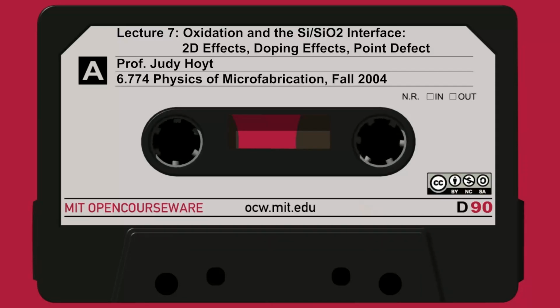We also talked a couple of times ago about interface charges that come along with oxidation. And this model on slide 38, while we're talking about atomic-level things, is an atomic-level cartoon or picture of what is actually causing the fixed charge and the density of interface states. Here's my amorphous SiO2 up here, and my crystal silicon. In the near interfacial region, there are believed to be a few interstitial silicon atoms.